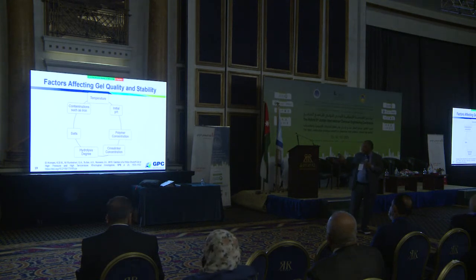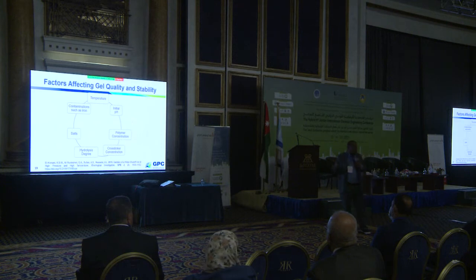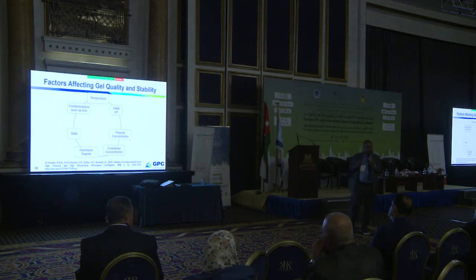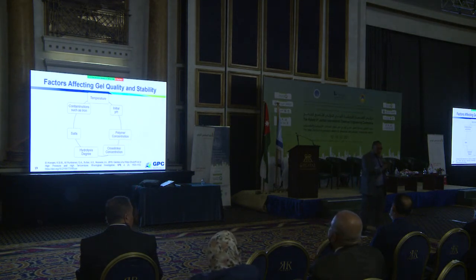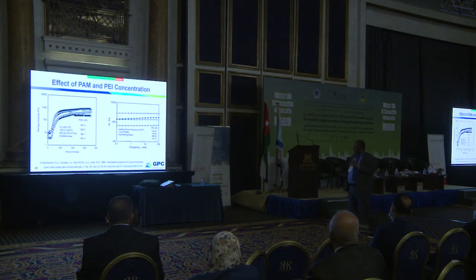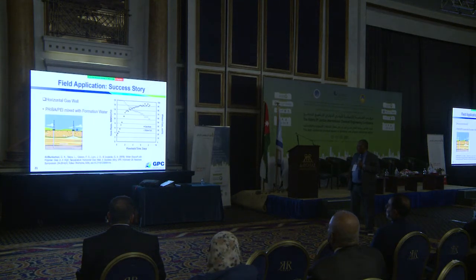Part of it is the concentration of polymer, salts, and initial pH. pH is very important. The degree of hydrolysis is also important. And all of these factors should be optimized to get the best formulation for the specific application. So if you have a specific application, you have to know the target zone, the temperature of that zone, the water salinity, the depth, and so on, so that you can design the right formulation. So we study here different parameters, and we develop the formulations.